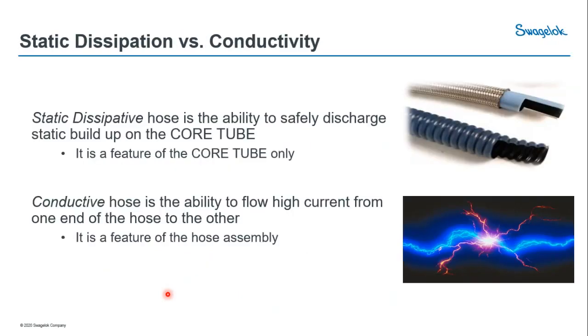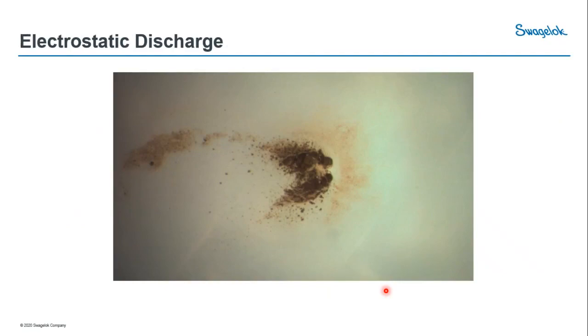So again, we want it to be conductive. You'll see here the carbon black comes in the convoluted, but also in the smooth bore. One of the things we always get asked is, will that carbon black leach into our product? No, it won't leach into your product, so it's very good that way. It's used quite a bit in steam applications, because steam at a high velocity through the hose can create a lot of static buildup. You'll see this is a silicone cover, and this is what it may look like on the outside. That's a hose where the static wasn't grounded, didn't use a carbon black core, and it went right up the side of the hose.